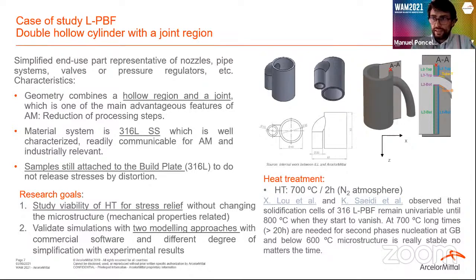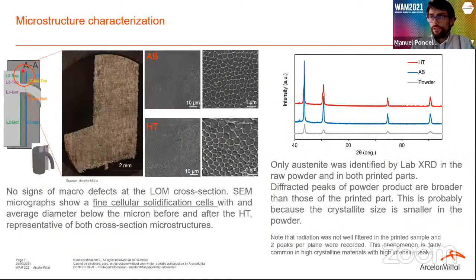And we have two initial goals. We were working with 316L. First was to study the viability of stress relief by a heat treatment without changing, or not changing much, the microstructure, because we want to guarantee the mechanical properties of the part, and validate two modeling approaches we use to predict residual stresses with different degrees of simplification. So we did a metallurgical analysis of both components, the sample as built and the sample heat treated. We had already developed the printing parameters for this steel, so we could assure a fully dense part without macroscopic defects. So there's no porosity or cracks inside.